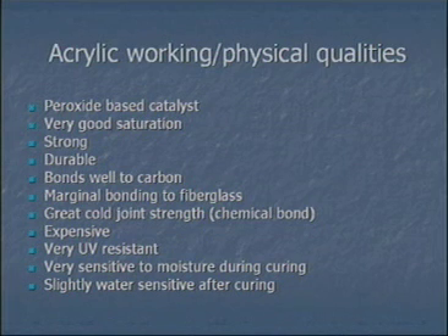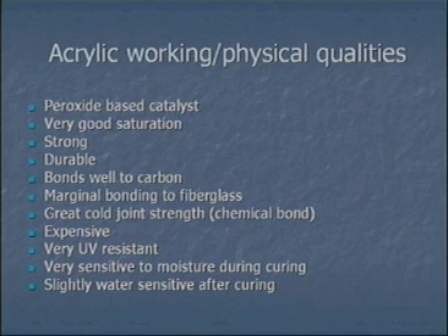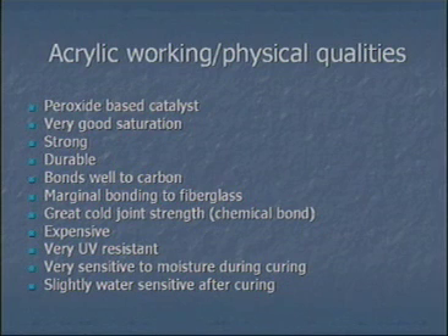They are very sensitive to moisture during curing. So if you have any moisture in your cast, in your PVA bags, in your positive model, it's going to destroy the whole lamination. So you have to be very cautious about keeping moisture out of your lamination while you're working with acrylic resins. And they're slightly water sensitive after curing. If you take acrylic and you place it in water for a long time, it'll kind of get cloudy looking and swell some. So you don't really want to have them in water all the time.